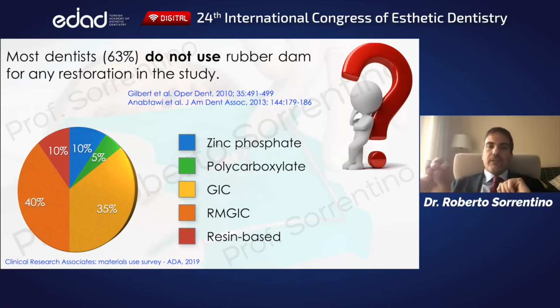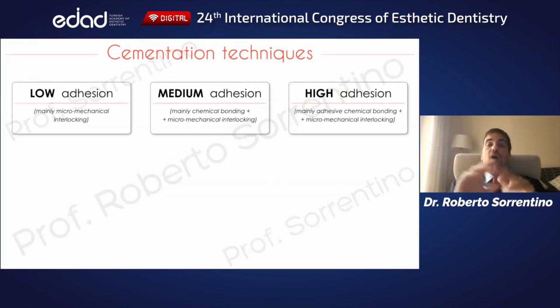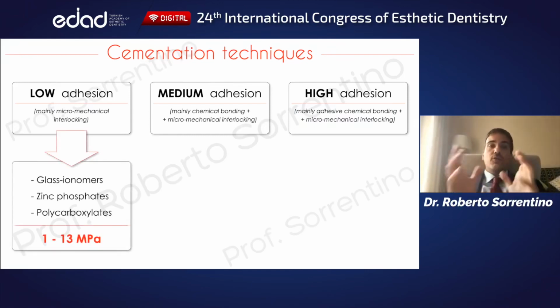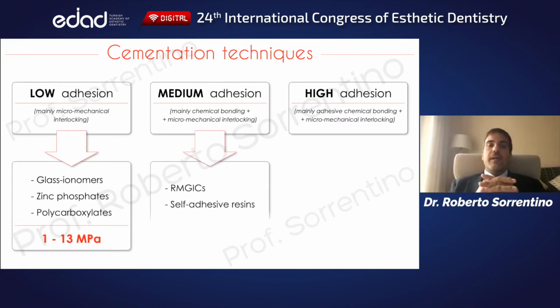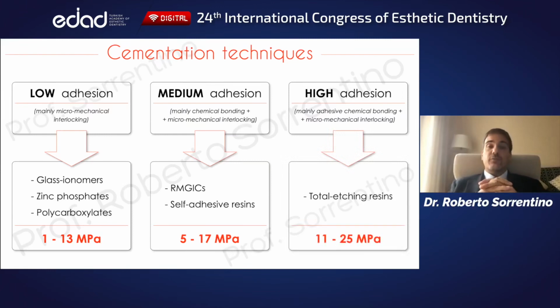So we have to point out that clinically different cementation techniques exist according to the clinical needs of the case and the type of luting agent. We can distinguish low micromechanical adhesion, mainly based on surface interlocking and using traditional water-based cements, medium chemical adhesion by means of simplified self-adhesive and resin-modified glass ionomer cements, and purely high adhesion using the adhesive chemical bonding offered by conventional total etch resin cements.